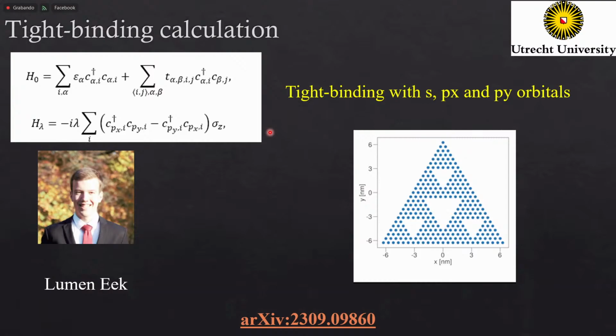The question is whether you can have more information from the experiments, especially the band structure of the material. Yes. So this part on the determinate states is really in the band structure. The band structure itself, we have some. With spectroscopy, you can have some information on that. This we do not try to match precisely. We look more at the density of states in space. But looking at this spectroscopy, we can actually see that the states are gapped in the bulk. I do not show this, but in the paper we actually have experimental data, at least. The band structure we do not show the theoretical one.